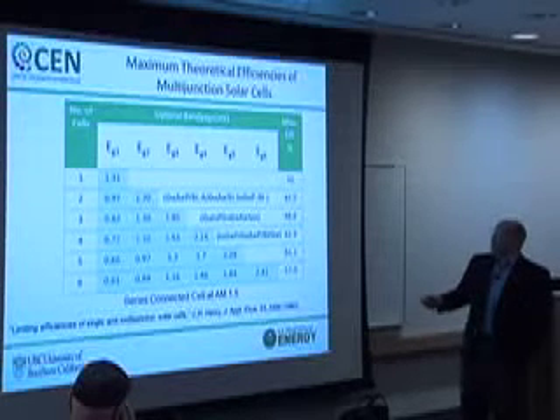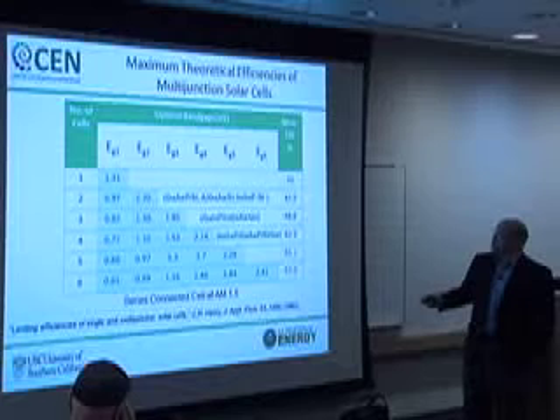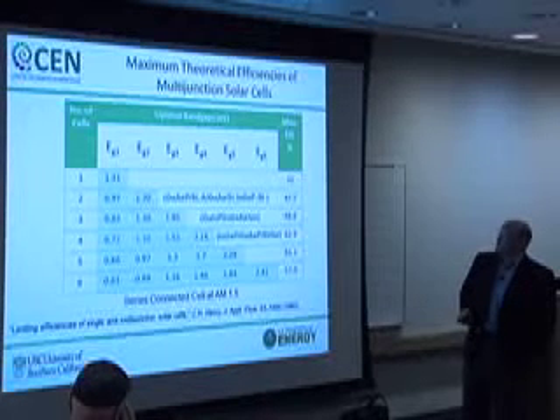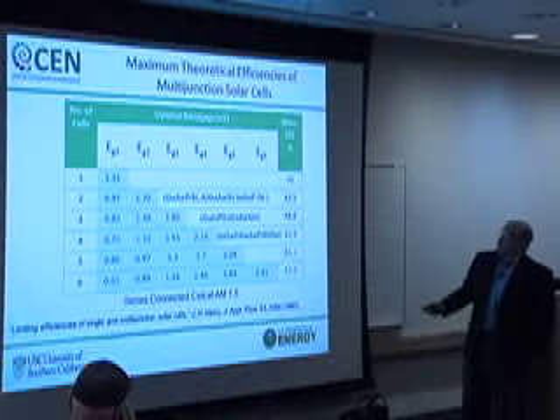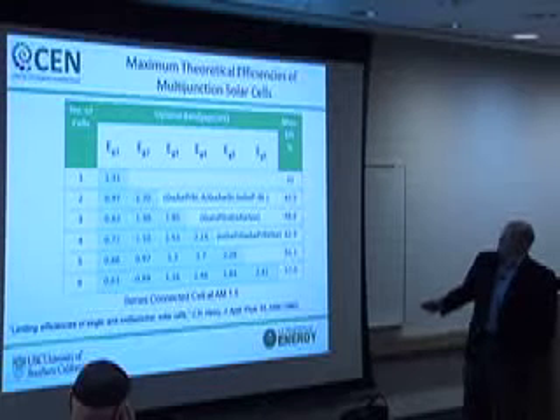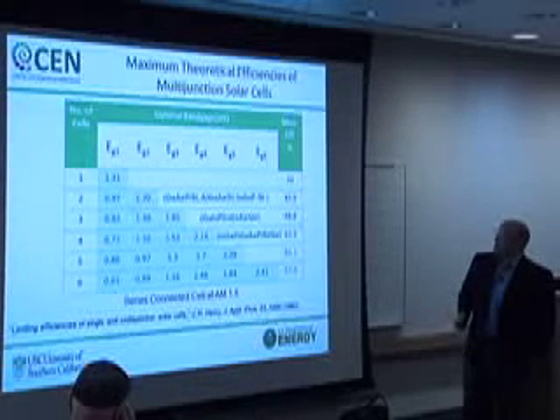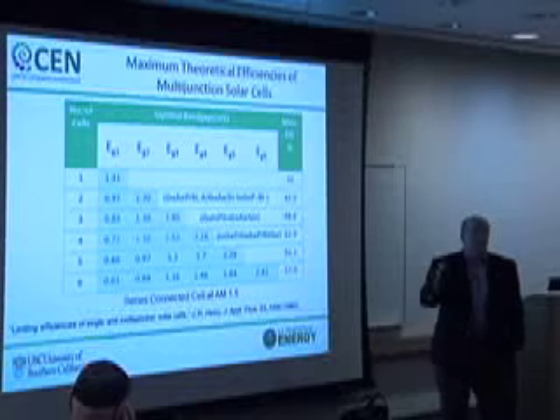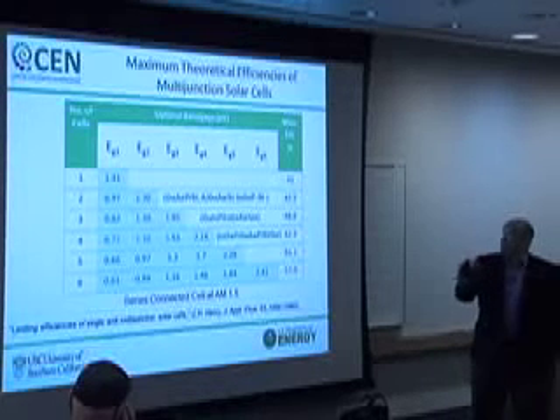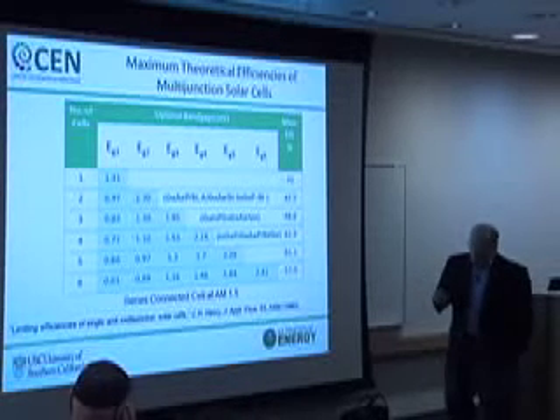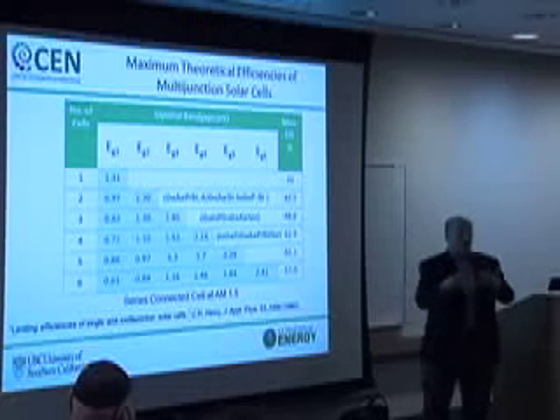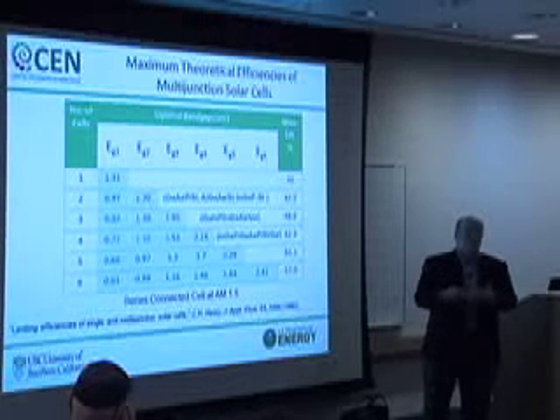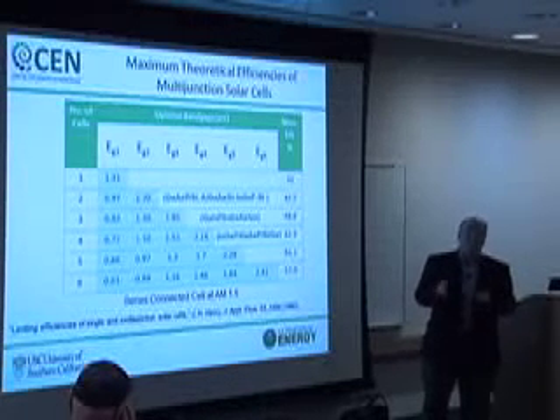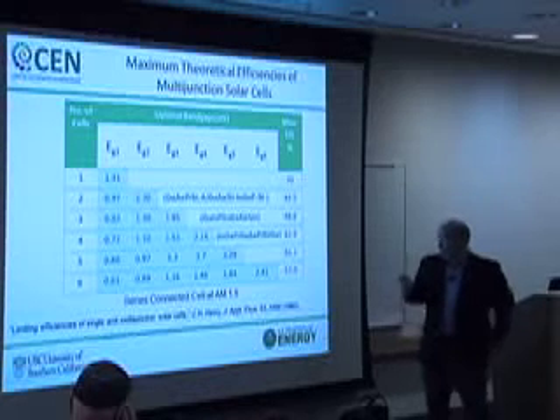So if you go to 3 junctions, then you can use germanium, indium gallium arsenide, and gallium indium phosphide, etc. You'll notice that in several of these possibilities, and incidentally, this is indicated without any concern about the lattice constants of the constituents. So we're not worried about lattice matching in this exercise.